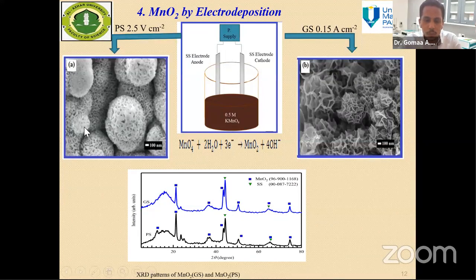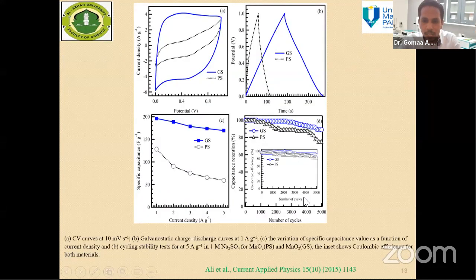And in both techniques, we successfully obtained manganese oxide with nanoflower morphology. But in one technique, the thickness of the sheets is thinner than the other one. And this material, also prepared from a chemical source using electrodeposition, shows excellent electrochemical behavior and high stability up to 5,000 cycles of charging the supercapacitor.